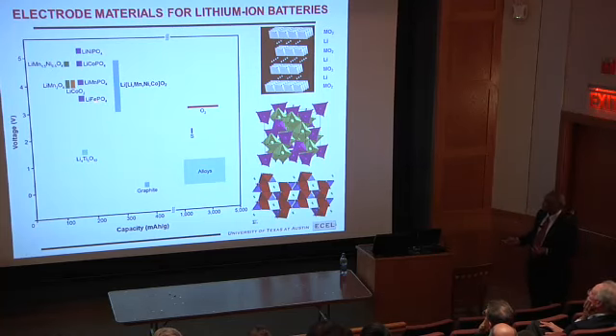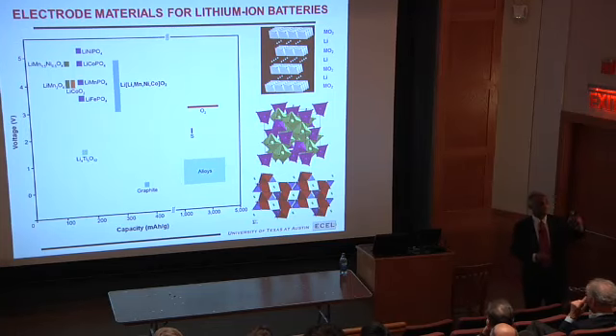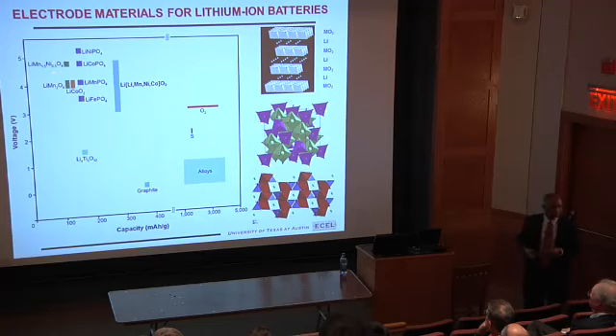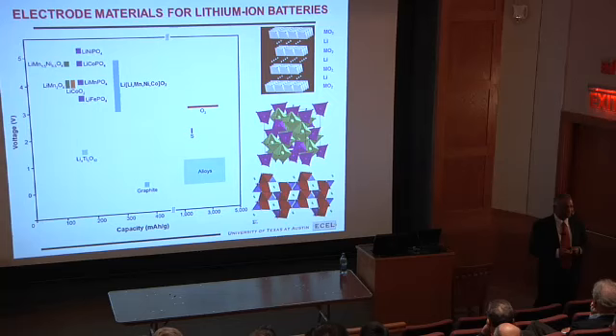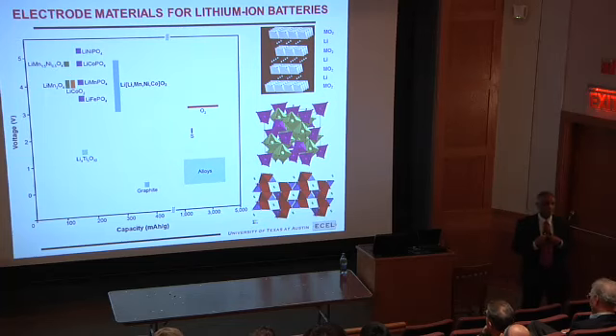So that material also has lower crystallographic density, and on top of it, to make it nano, you coat with carbon. So volumetric energy density really goes down, not good for automobiles. And all these three are the only three right now available. And all three were originally identified by somebody called Professor John B. Goodenough. And I had the fortune of going to him as a postdoc when he was in Oxford. That's where I met him.